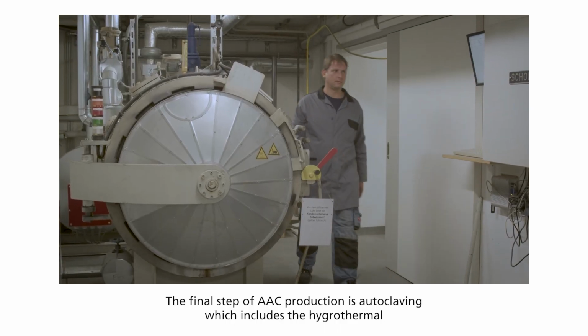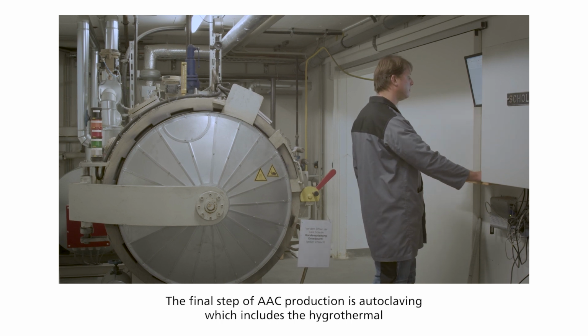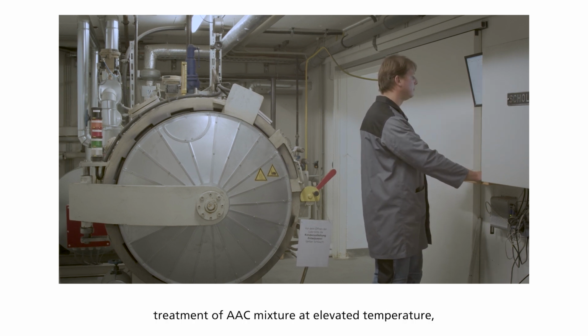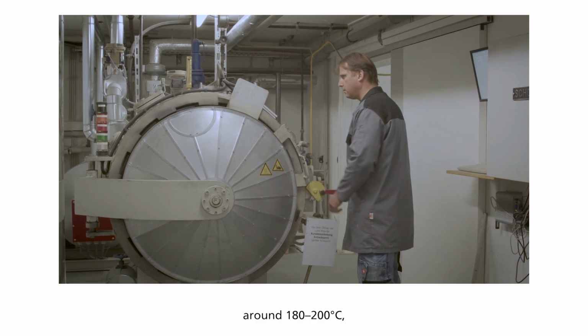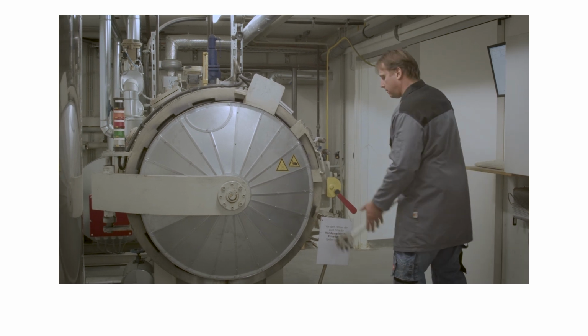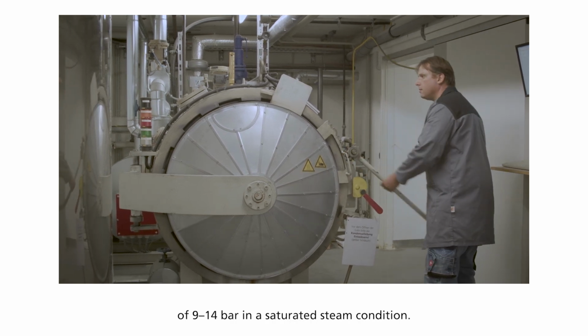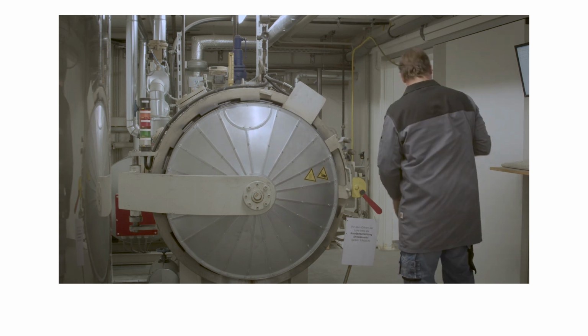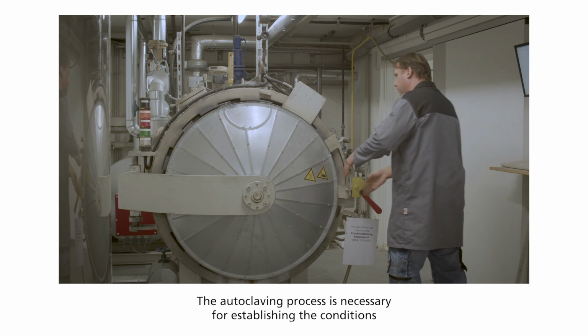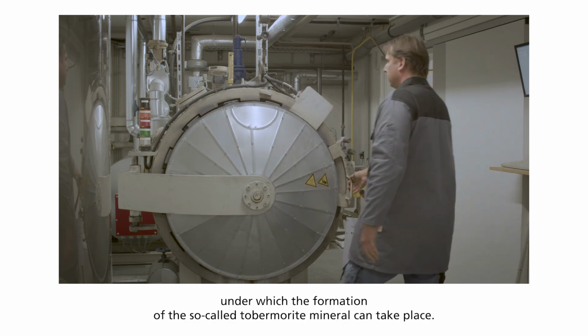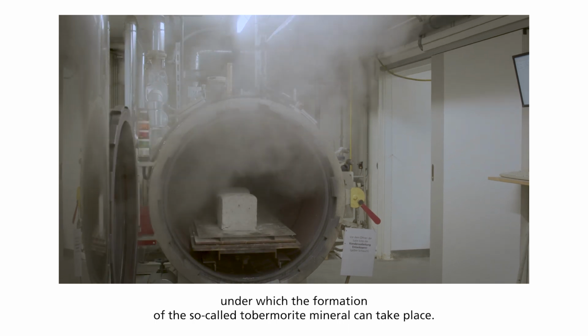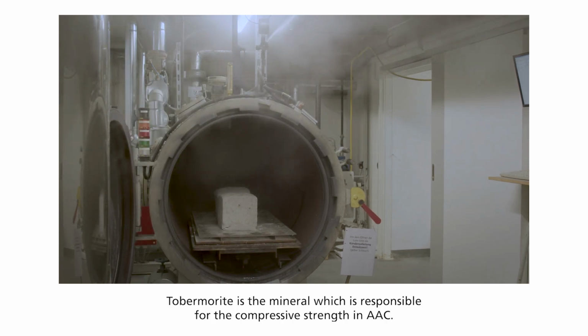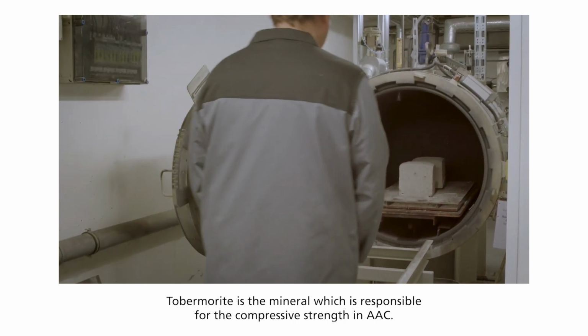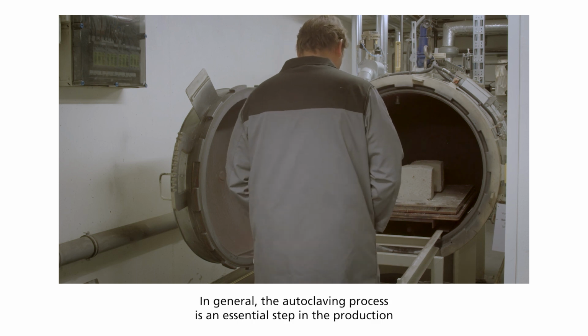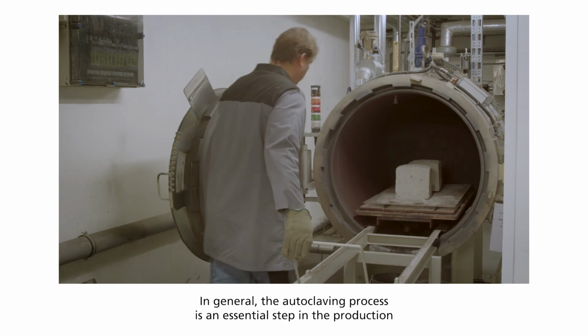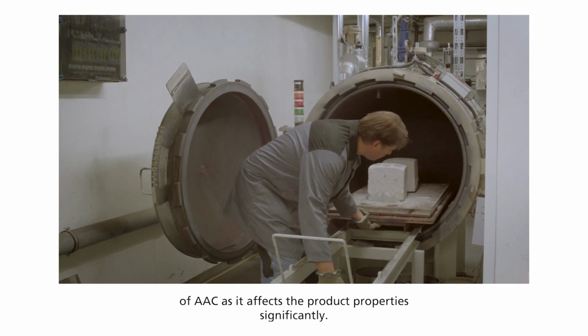The final step of AAC production is autoclaving, which includes the hydrothermal treatment of AAC mixtures at elevated temperatures, typically between 180 and 200 degrees Celsius, and a corresponding pressure of about 9 to 14 bar in a saturated steam condition. The autoclaving process is necessary for establishing the conditions under which the formation of the so-called tobermorite mineral can take place in AAC. Tobermorite is the mineral which is responsible for the compressive strength in AAC. In general, the autoclaving process is an essential step in the production of AAC as it affects the product properties significantly.